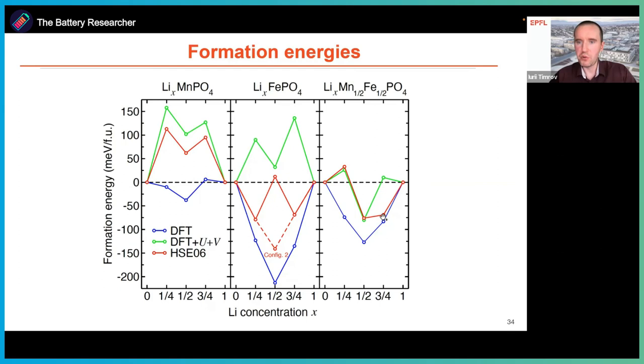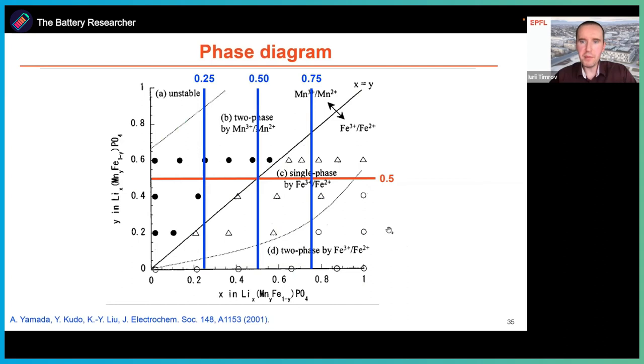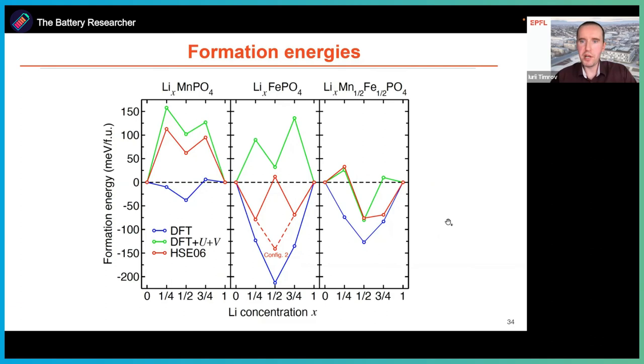And finally, at concentration 1/2, from experiments, we can't really conclude what's happening because it's really the borderline between two regions, two phase and single phase. So we can't make any conclusions. But from our simulations, we find that both hybrid functional and DFT plus U plus V give essentially the same result. And these are negative formation energies, which suggests that it must be a single phase process.